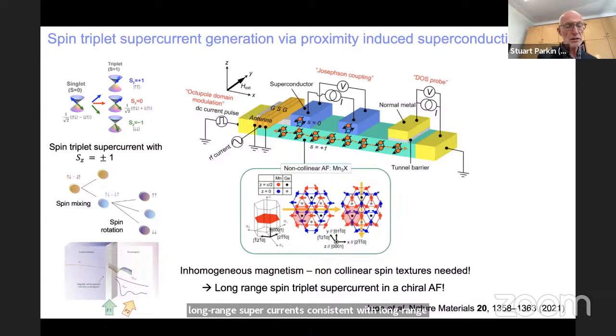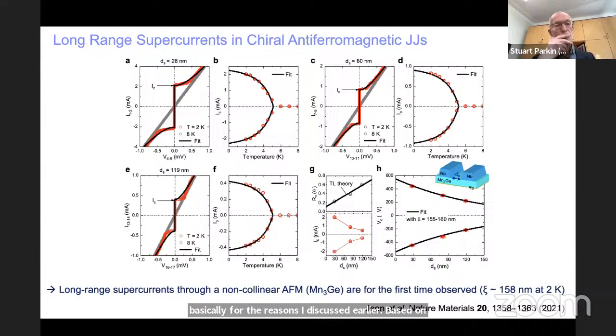We think this is a very exciting possibility, and it's basically for the reasons I discussed earlier, based on these predictions of Buzdin and Bergeret and others. How do we see this? Then we look basically at the current flowing between those two niobium electrodes through manganese-3 germanium for different separations of those electrodes. And the current, shown in A on the vertical axis as a function of the voltage, shown on the x-axis, the voltage is 0, but current is flowing, and the current flows until you exceed a certain critical current, and then the system becomes normal. And that critical current for superconductivity will, of course, decrease with temperature, and it will also decrease with increasing separation of these niobium electrodes. Nevertheless, we showed that we could see these supercurrents flowing over very large distances with a characteristic length of more than 150 nanometers.